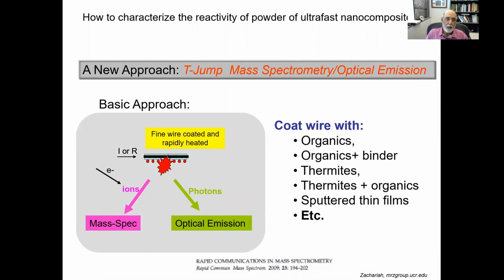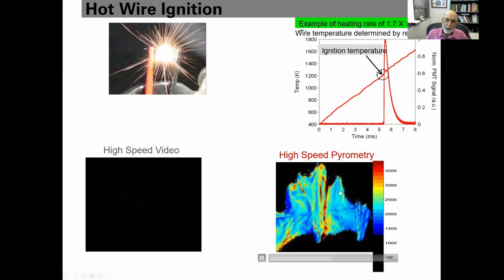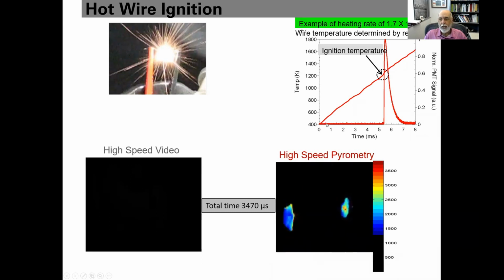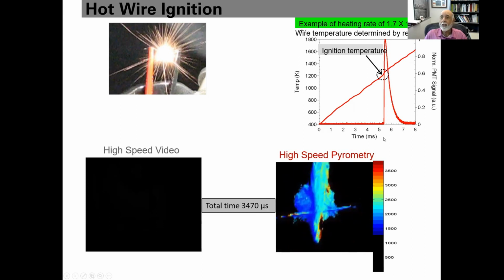One approach is to do rapid heating on a wire. You coat your material on a wire, you heat this wire by Joule heating, and then things are going to come off the wire, which you can detect, or light will be emitted, which you can detect. And so this is what an image looks like from an event on this wire. And we can do color pyrometry, which I'll discuss later, to get the temperature profile. And the wire itself can act as a thermometer. So this is the wire being ramped in time. And the light emission is basically when ignition occurs. And this gives us the ignition temperature. So you can use the wire as a thermometer to get ignition temperature.